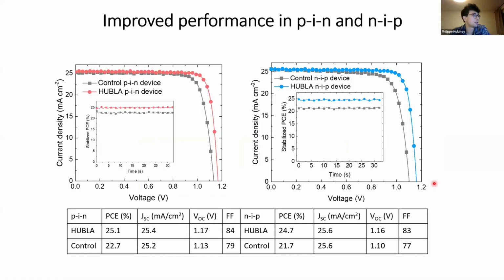And we also proved this in devices. And we find a significantly improved stability and efficiency for both PIN and NIP. So for PIN, we get roughly 25%, and for the control around 22.7%, especially in VOC and fill factor. But also for the NIP cells, we find an improvement in efficiency of around 3%.